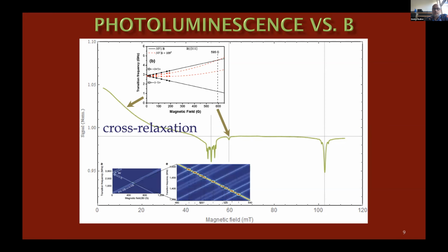And then apart from the NV centers, you have other things like the substitutional nitrogen atoms that are not paired with NVs. These are called P1 centers, and they also have non-zero spin, spin 1/2, and there is also nuclear spin involved. And in the end, you have all kinds of crossings here.